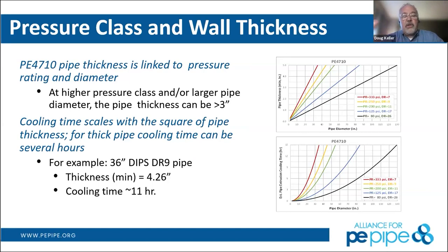As we go to larger and larger diameter pipe, keeping that same ratio, keeping that same operating pressure of 200 PSI, we are now in the position where, for example, a 36-inch DR9 pipe in this case would have a minimum wall thickness of 4¼ inches. When we go to extrude that material, we heat the polyethylene up above its melting point, and then that pipe is extruded and it goes down through a set of cooling tanks. Well, it takes about 11 hours for a 4.25-inch wall pipe to cool down to the point that that material has solidified in the middle of the pipe, because it solidifies from the inside and the outside moving in. Next slide.